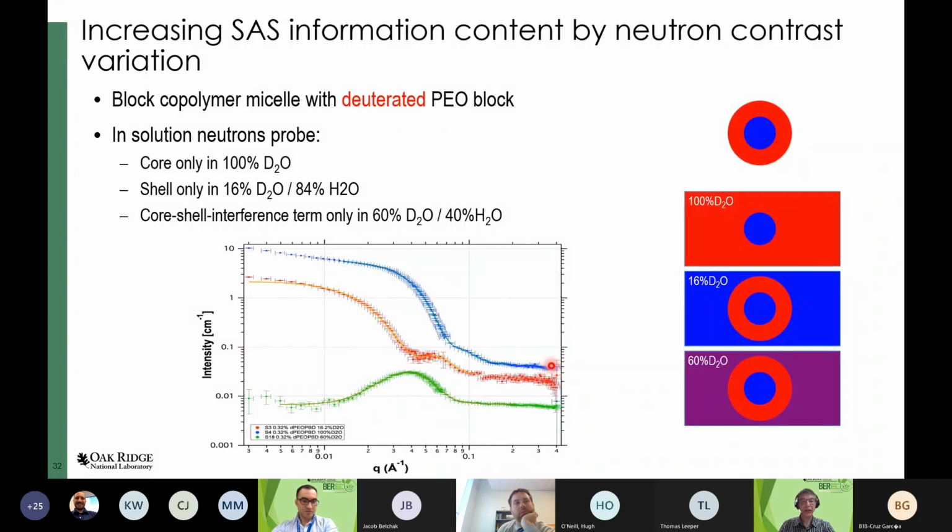One of the things that you will notice in a core shell structure is that when you see the shell, you're getting more of an amplification of the secondary peak relative to just a simple sphere like this one. But if you have a distribution of core shell particles, that would mean you would have multiple of these curves that have their minima all in different positions.